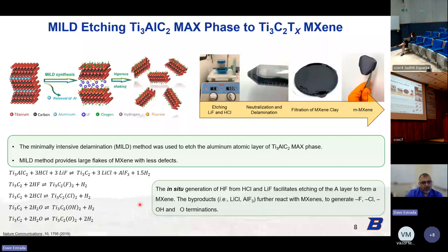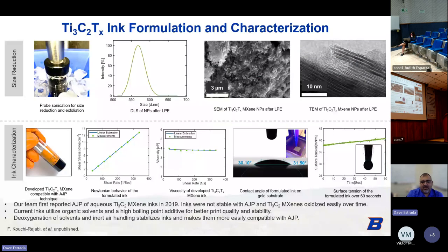And so we can end up with fluorine, hydroxyls, hydrogen, oxygen on the surface of the flake, which can then impact their properties for different applications and their performance for different applications. Typically, these are large microscale flakes that we get from the etch process. So if we want to make them compatible with the material jetting platforms, we have to reduce the particle size.